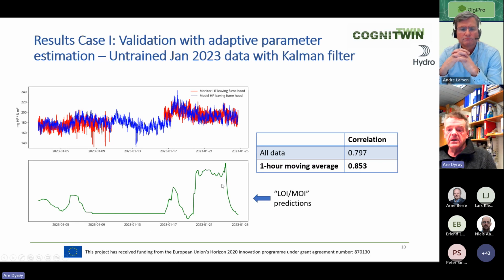And what we then found with the model was that we had a monitor that was measuring the HF content of the raw gas. We see that that one every now and then drops out due to obscuration of the lenses used on this laser-based system. However, whenever the model comes back on, you can see that it will represent the same value as measured in the system, even meaning that we can run for a period of time without the actual measurement, which gives us a good trust in the model that was put up for this case.